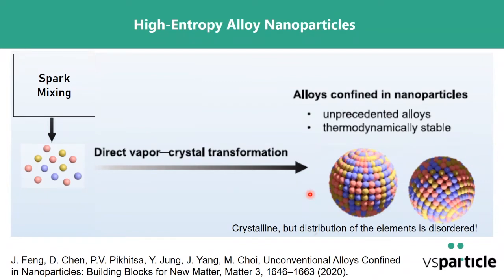It comes from the Gibbs equation, where the Gibbs free energy has a negative term with entropy in it, and the higher the entropy, the more stable the particles are. And of course, the same group in the same paper cited here already showed an example where such a material consisting of between 5 and 10 different elements is useful for catalysis.